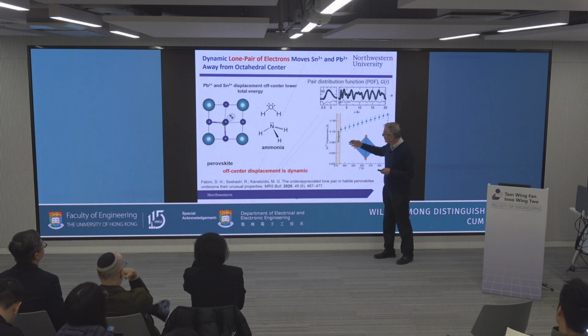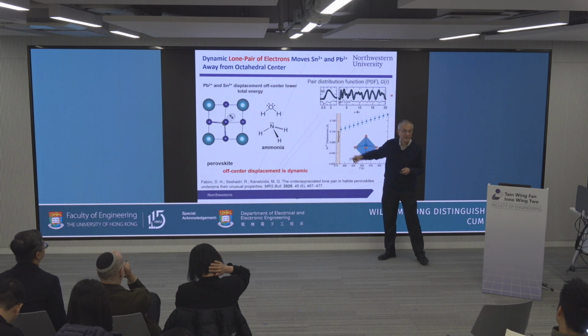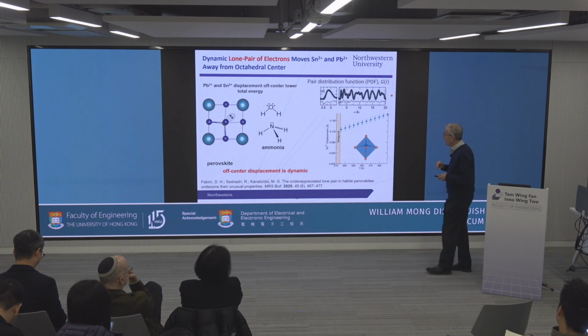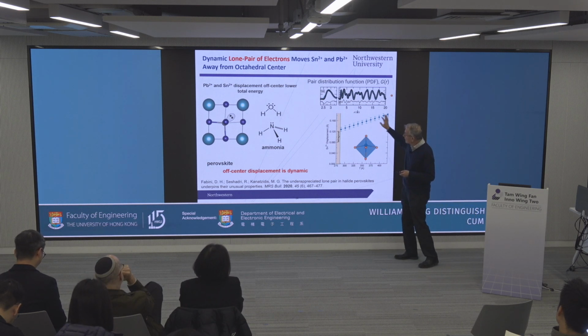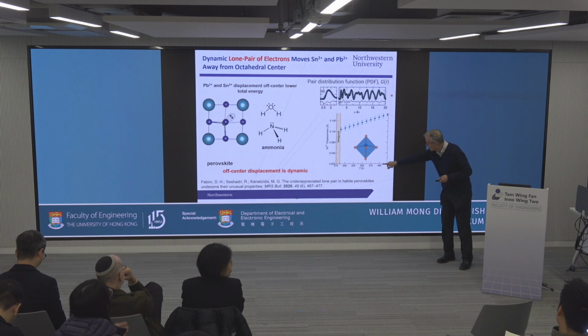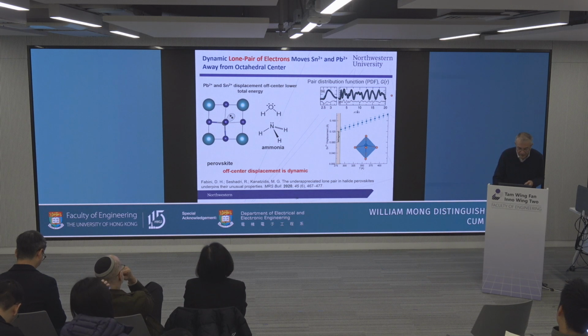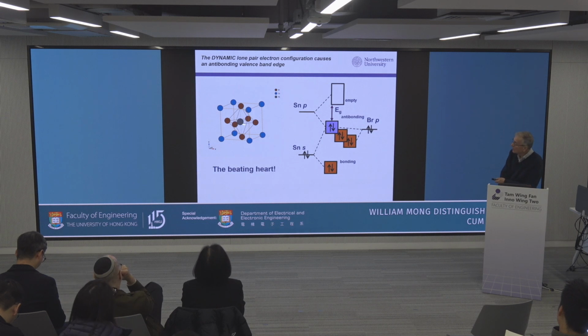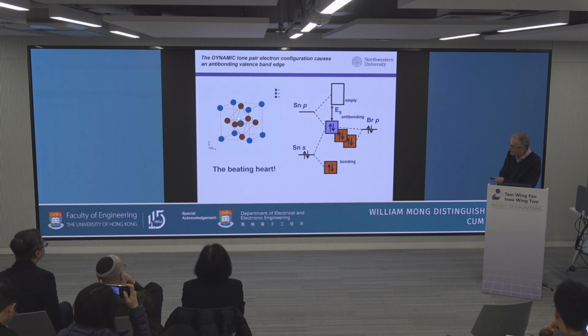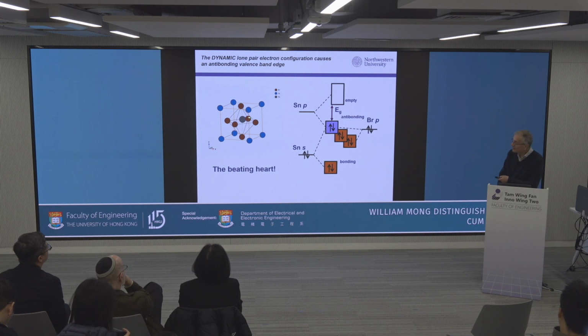And in tin, we quantify 0.1 angstrom away from the center. In lead, it is about 0.08 angstroms. But it's dynamic, okay? And this is increasing. It gets even more as you heat it up. So why is that now? What's happening here? So we have this picture. It's a simplistic picture because some of these other atoms as well are moving, but this is what initiates this process. It never settles. It's a fight between the crystallography, which requires high symmetry, and the chemistry, which requires low symmetry. And nobody wins. And so you have this eternal situation.